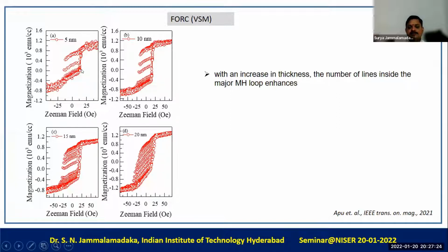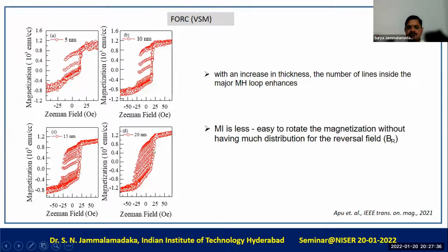This could be due to the fact that, as I mentioned, the density of the grains within the 5 nanometer film is very less. The magnetostatic interactions are very less, and because the density of the film is very less, the distribution of the field is very less. That is the reason why we don't see many lines in the 5 nanometer FORC curve. However, as the thickness of the film increases, the magnetostatic interactions are more and more, which leads to more and more reversal fields.